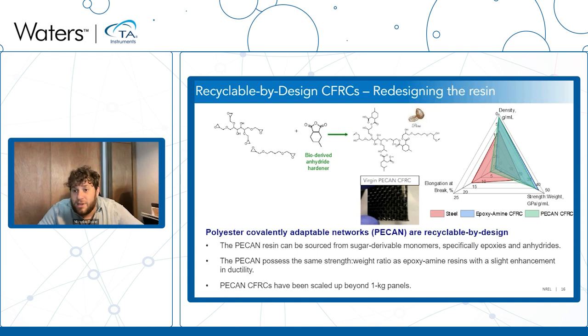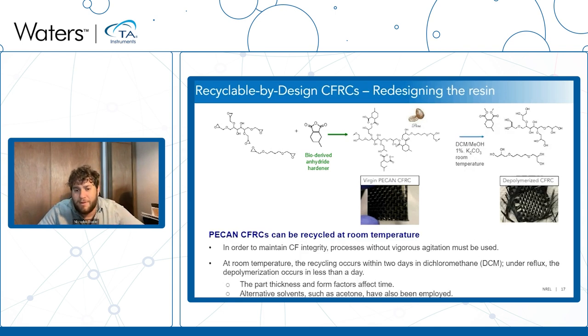But the big thing to note is we've been able to show that we can redesign from bio-based derived resources a resin from polyesters that looks and performs a lot like an epoxy-amine resin. The big thing, though, is we now have polyesters in the backbone of this material.